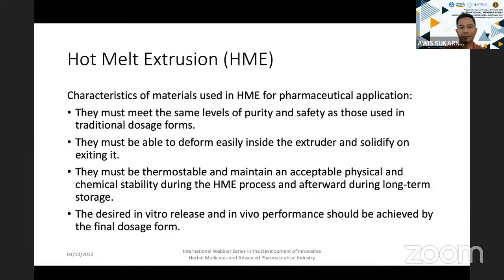And then the third one, it must be thermostable and maintain an acceptable physical and chemical stability during the HME process and afterward during long-term storage. This is what I mentioned just now. The sample that you use needs to be stable at a certain temperature, because again it's going to apply heat, and if your sample is very heat sensitive or the degradation point is too low, then you cannot use the HME technique for the sample.